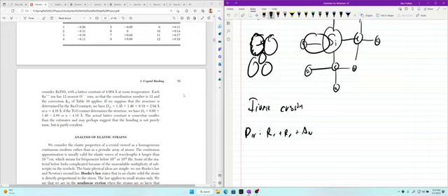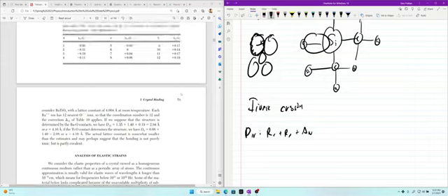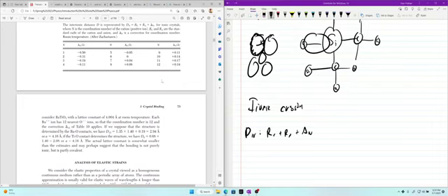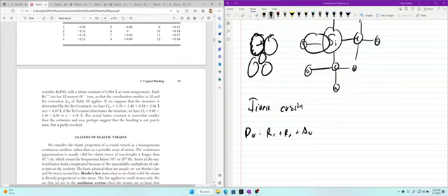The coordination number is 12, and the correction for 12 applies, so 0.19. If we suppose that the structure is determined by barium-oxygen contacts, D12 is 1.35 for barium, 1.4 for oxygen, plus 0.19 the correction, is 2.94 angstroms, or the lattice constant is 4.16 angstroms.